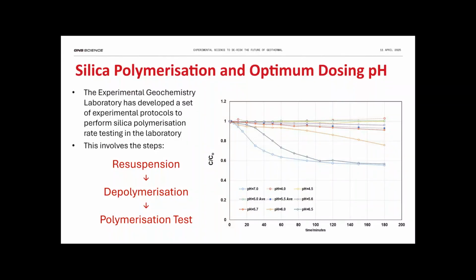Then we have to depolymerize the sample, which is done through use of the flow-through equipment. So we actually just run the brine through the flow-through at 300 degrees, and it redissolves the silica. And then we take that brine, and it's preserved at low pH. We take it to the laboratory benchtop, and we do polymerization testing by adjusting the pH.